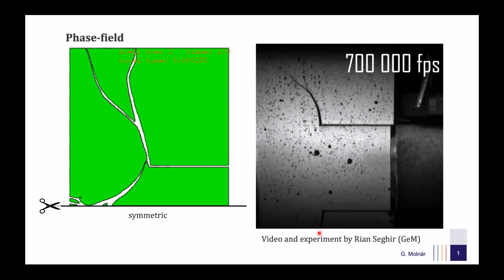Remarkably, using just two material parameters, the phase field model is able to quantitatively reproduce the crack's initiation, propagation, and branching. In this talk, I will demonstrate how this is possible through the diffuse crack representation employed by this technique. I will also discuss the additional phenomena we can model using the phase field approach, how to identify the regularization crack length in real materials, and how we can use this length scale to homogenize the toughness of metamaterials, a property traditionally considered non-local.